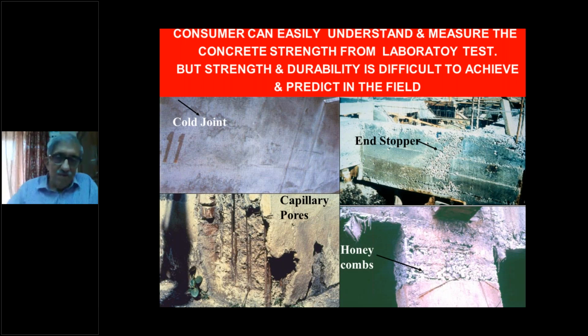The main reason being, when we cast a cube under laboratory conditions, the temperature is around 27 degrees centigrade and the humidity could be around 80 to 90%. Now, the most important thing one must understand is the cube cast and tested is well compacted, well leveled and filled, and also, as far as possible, free from entrapped air and does not have any honeycombs. While on the site, we make sure that the same conditions are achieved, but it is not generally so.